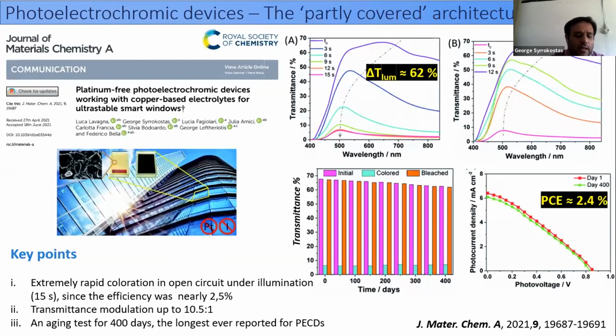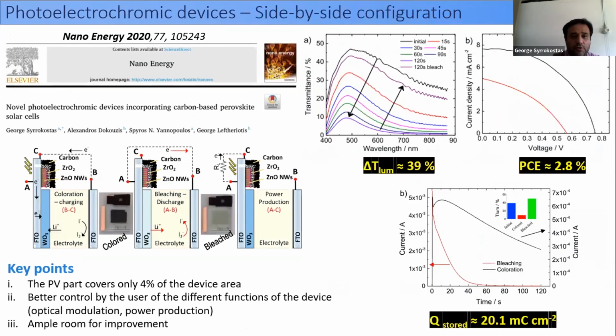Later, we used an electrolyte having a copper-based redox couple to replace the iodide-triiodide redox couple. In this case, we wanted to solve the corrosion problems that are usually met with the iodide-triiodide redox couple. Also, we used a very thin graphene nanoplatelet film instead of the platinum film. In this case, the optical modulation was above 60%, and the coloration time was very fast, only a few seconds. Again, these devices were extremely stable even after 400 days of continuous operation.